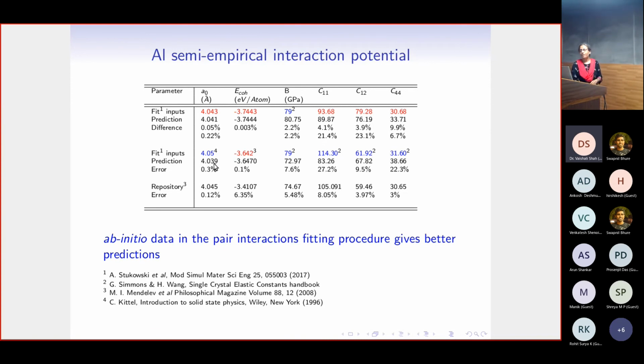What we see again is that we are doing a fairly good job when it comes to the structure and the energetics part. But when it comes to the elastic constants, it is still not doing really well. It simply means that we need to fine tune our fitting procedure a little bit, so that these elastic constants are predicted reasonably well, which we will do.